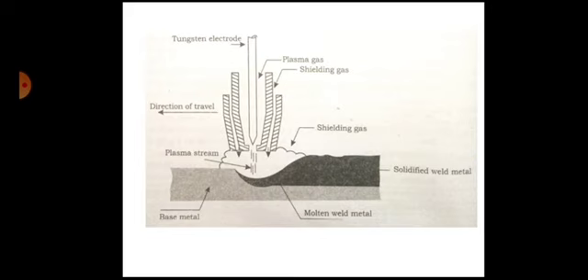Typical gas flow rates are 2 to 40 liters per minute with the lower rates for orifice gas and higher rates for shielding gas.